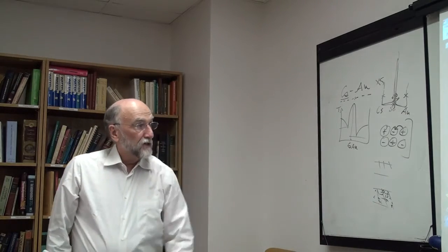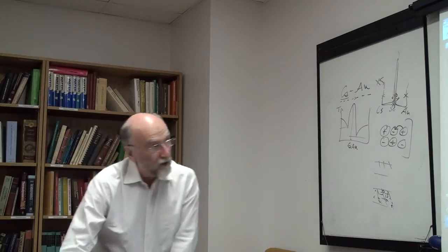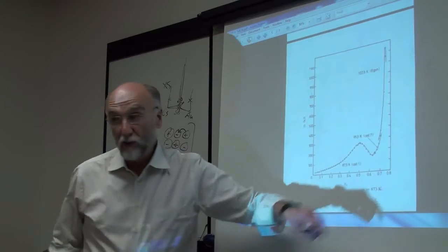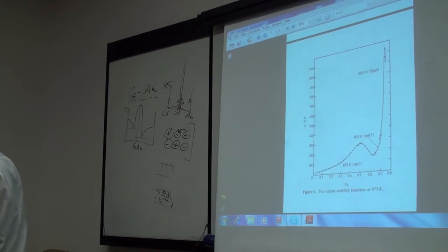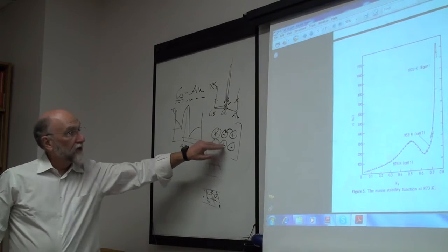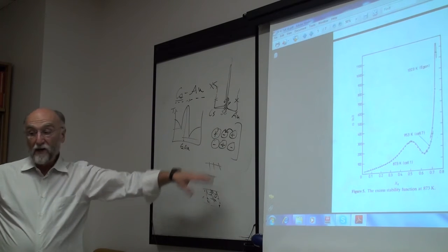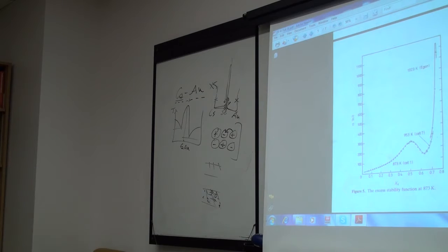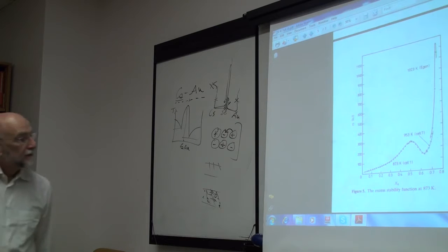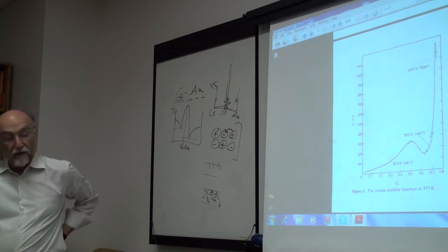These other materials such as potassium tellurium aren't that flagrant, so as you go across here it still remains an electronic conductor, but the electronic conduction goes way down around the compositions of the maximum short-range ordering because you're getting a lot of electron localization and you don't have many free electrons left as you do in the metal. So these are kind of interesting materials. People talked about them as ionic liquid alloys. So, I just want to look at that qualitatively.